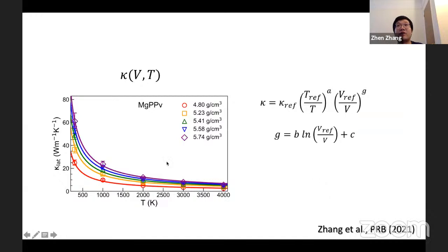Kappa was obtained at different volumes and temperatures. To obtain the VT dependence of kappa, geoscientists often fit kappa to the relation shown on the right. T reference and V reference are the chosen reference temperature and reference volume. The choice of V_ref and T_ref is not unique, but does not change the VT dependence of kappa. Kappa ref, A, B, and C are fitting parameters. By fitting to this relation, we obtain kappa as a function of VT, shown as solid curves.